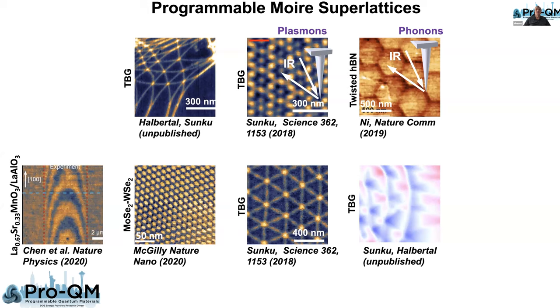I already talked about plasmon polaritons, I'll skip this part. You can also visualize local DC transport using these nano-optical methods. This map that's unpublished, but now it's going to be recorded. This map is essentially a map of local DC conductivity. In this experiment, we still illuminate the tip with light, but we record a photocurrent, and it visualizes this network of excessive conductivity at the domain walls.